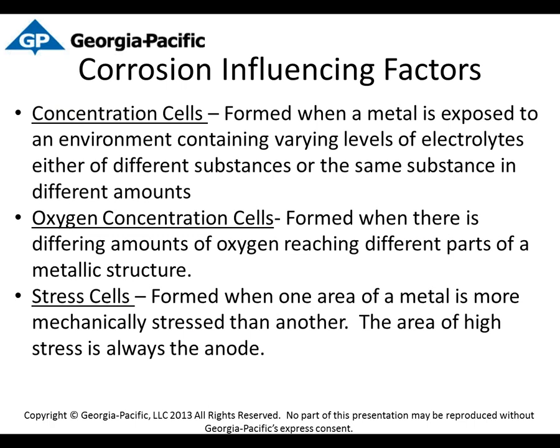Specifically, oxygen concentration cells, where you can get areas of very, very low concentrations of oxygen beneath the microbes on the pipe surface. That's particularly important when you're dealing with stainless steels, because the reason they're stainless is that they have a very, very thin passive film formed by chromium oxide on the surface. And if there is no oxygen present in the environment to replenish that chromium oxide, then it's easy for the steel beneath it to corrode.